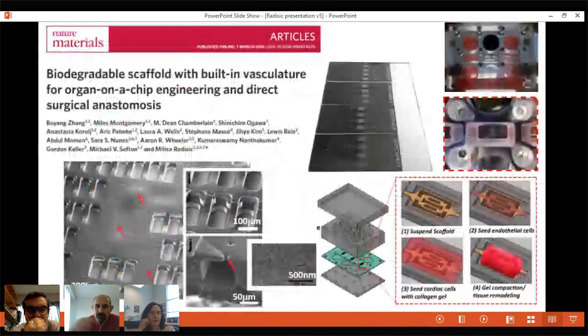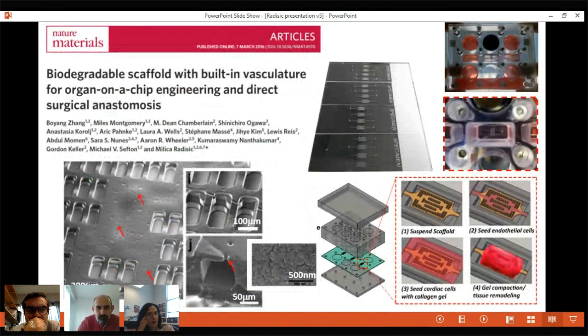This work enabled us to create the vasculature that is both mechanically stable for handling and permeable, because polymers usually suffer from this limitation that you cannot really control their permeability very well. So what Boyang has done here, he incorporated two levels of permeability, one through these nanopores and the other one through microholes. And the microholes also enable connection of endothelium to the surrounding space where the tissues are located.